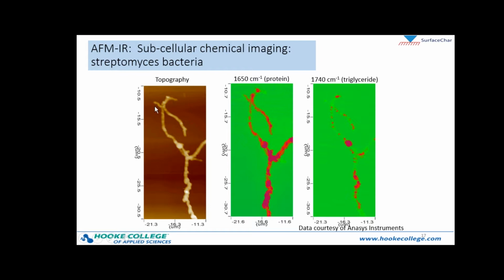So here is a topography image of the bacteria. And then the IR image was zeroed in at a particular peak, 1650 wave numbers, which corresponds to a protein, and then 1740 wave numbers, which corresponds to the triglyceride. And you could easily map the distribution of these two components in this bacteria and see where these individual components are with very high resolution.